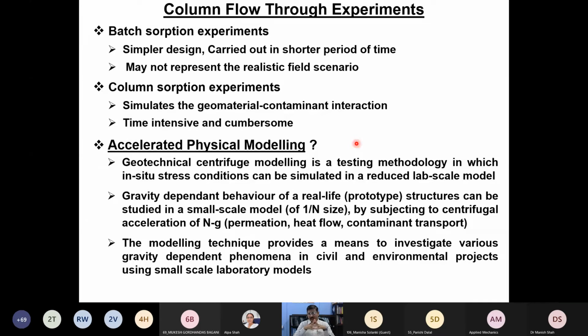But since the hydraulic conductivity is very, very low, sometimes these materials also have a very high sorption. Even though 1000 ppm is going in, most of the material is getting attenuated within the system. As a result, you may not get anything out of it. So you may have to conduct the column experiments for maybe 5 to 6 years.